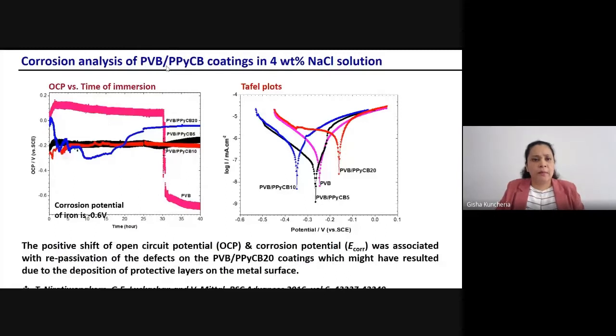So coming to my sample, polyvinyl butyral with the polypyrrole coatings. I measured the open circuit potential of the coatings. I prepared three coatings along with a pure PVB coating, and all four coatings were immersed in 4 weight percent sodium chloride solution, and I continuously measured the open circuit potential over 40 hours.